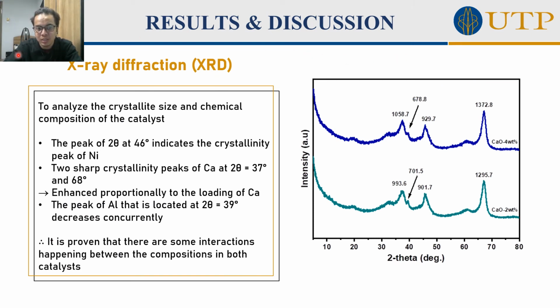So the first characterization is X-ray diffraction, XRD. This XRD is to analyze the crystallite size and chemical composition of the catalyst. This is the XRD pattern that we have obtained from the analytical lab. From here, we can see the peak of 2 theta at 46 degrees indicates the crystallinity peak of Ni, which is this one, this and this one, for 4% and 2% of catalyst, and two sharp crystallinity peaks of Ca at 2 theta 37 and 68 degrees, which is this one and this one, for 2%, and this one for 4% of CaO, and it is enhanced proportionally to the loading of Ca.